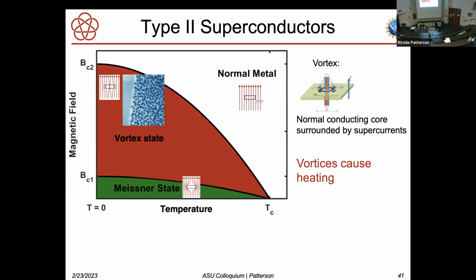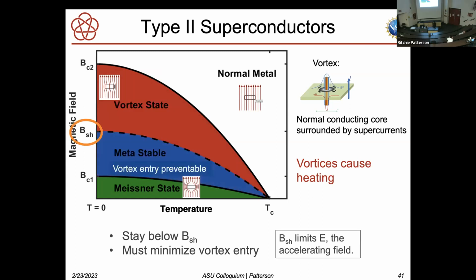And in the vortex state, vortices can penetrate into your superconductor. Vortices are bad because they cause heating. In the presence of the AC field, your vortices are going back and forth like that. That's heating. It turns out there's a metastable state where vortex entry is technically allowed, but preventable. This is sort of like supersaturation of a cloud with water. So in reality, superconducting RF cavities operate inside this metastable state.